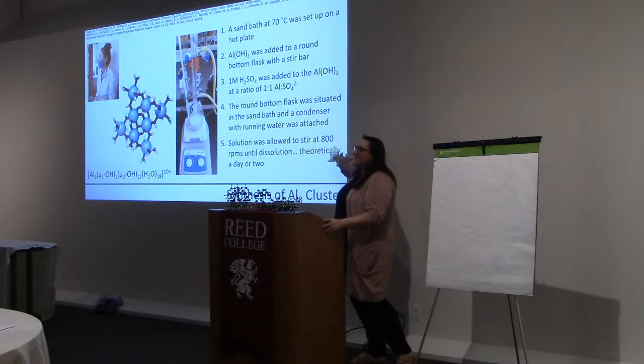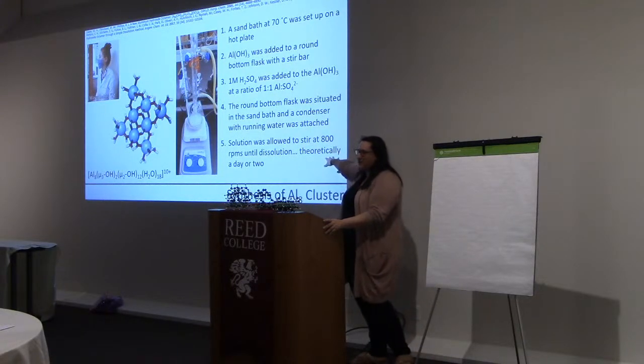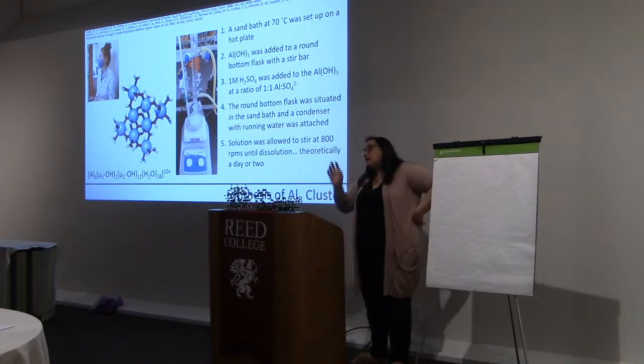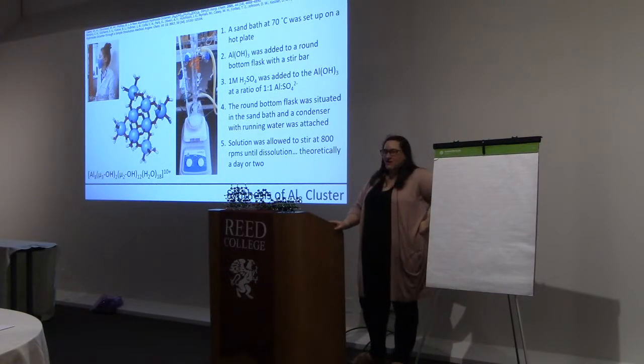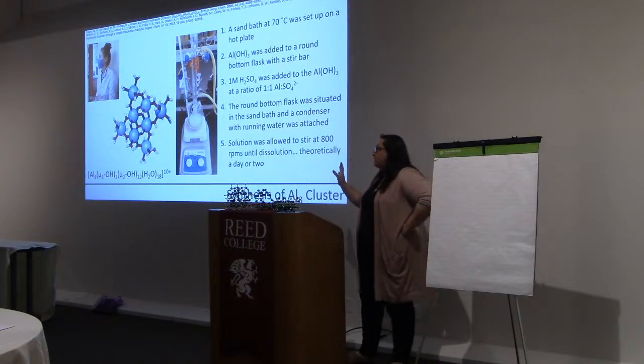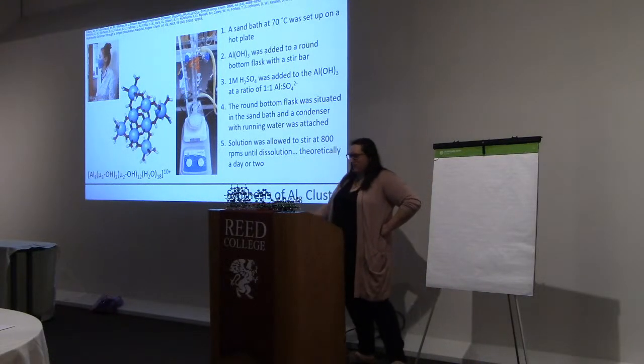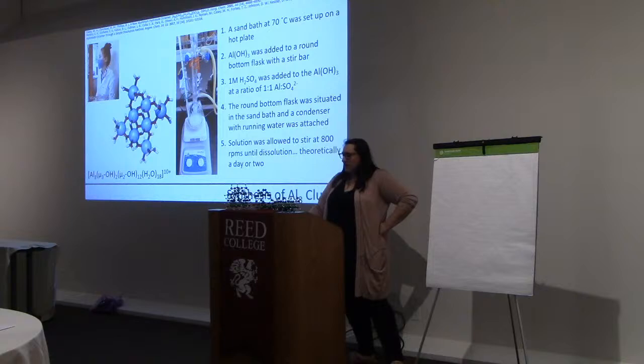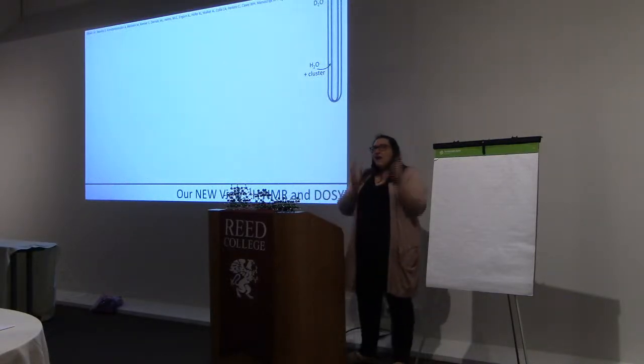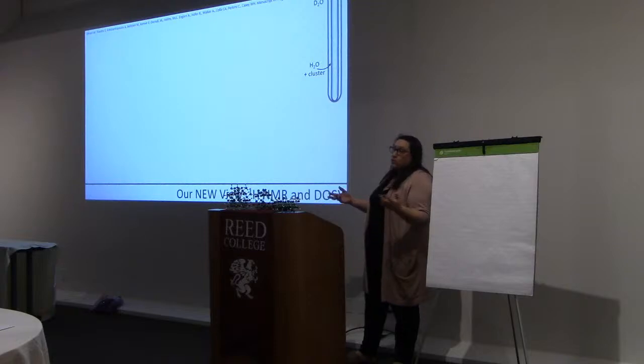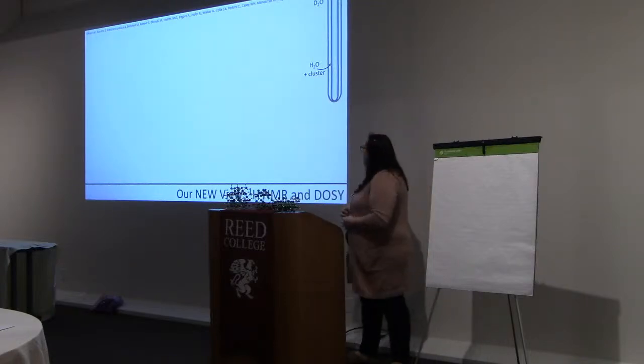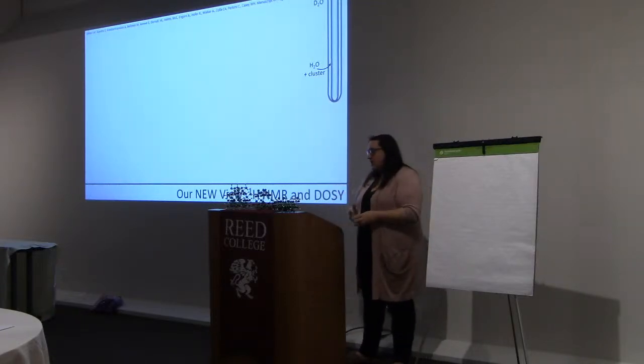Theoretically, after 2 days, it should dissolve. So she's taking aluminum hydroxide, putting it with sulfuric acid. It's supposed to dissolve. But so far we have been very much struggling with this. So that is a to-do to finish a future experiment to get this cluster synthesized. So now that we have a nice little stockpile of 3 of these clusters, the next goal was to start looking at them with proton NMR.